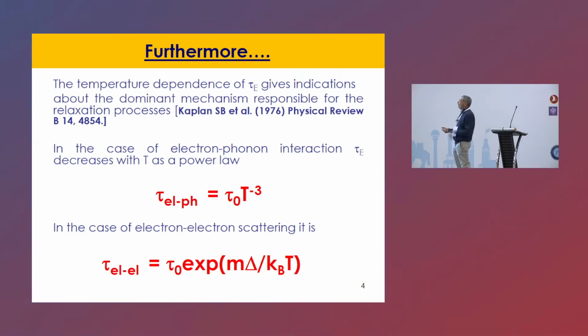So the temperature dependence of tau will give information about the mechanism which is in play in the dissipation, in the quasiparticle relaxation time. If the interaction is mainly due to electron-phonon, tau goes like a power of -3 with the temperature. In the case of electron-electron scattering, the dependence is more exponential. So from these two temperature dependences, you can understand what the main relevant mechanism of dissipation in the quasiparticles is.